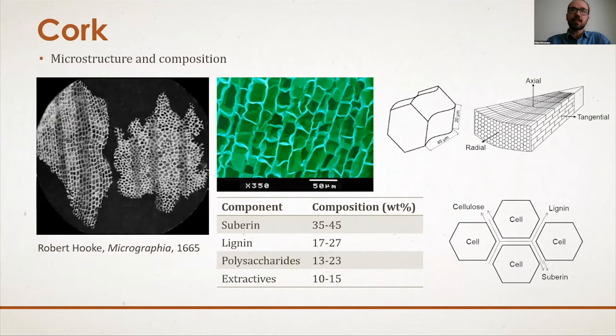It can be explained by its cellular microstructure and chemical composition of the cell walls. So the prismatic closed microstructure of this material was first reported by Robert Hooke in the 17th century. The solid volume fraction corresponds to 15% of its total volume, which explains its low density. Cork cell walls have usually a thickness of 2 micrometers, and they are mainly composed of suberin in association with the lignin and the lesser content of polysaccharides such as hemicellulose or cellulose.